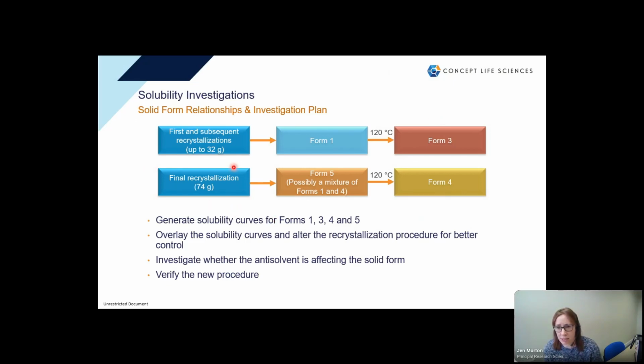Our final recrystallization of 74 grams gave us form 5, which is the one that we believe to be a mixture of forms 1 and 4. And when heated at 120 degrees, that converted to form 4. So we're now in the position where we believe that forms 3 and 4 are more stable than 1 and 5.